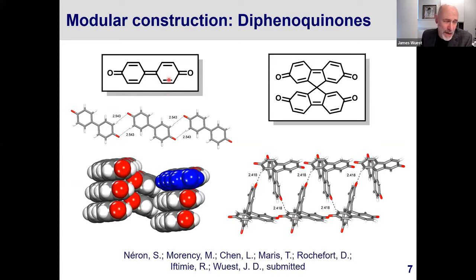And so we've made these compounds, characterized them by single crystal X-ray diffraction, cyclic voltammetry, and many other techniques. And I'll summarize here what we see in this case. This compound forms chains. The chains are held together by CHO hydrogen bonding. The chains stack, and the stacks are related by a sort of herringbone arrangement with adjacent stacks, as I show you here on the lower left. One of the diphenoquinone molecules is highlighted in blue. We've extended this work to much more exotic structures, in which, for example, two of these diphenoquinone units are linked in a spiro bifluorene type of structure. We characterized this compound. Again, it forms an interesting structure held together by CHO hydrogen bonds.